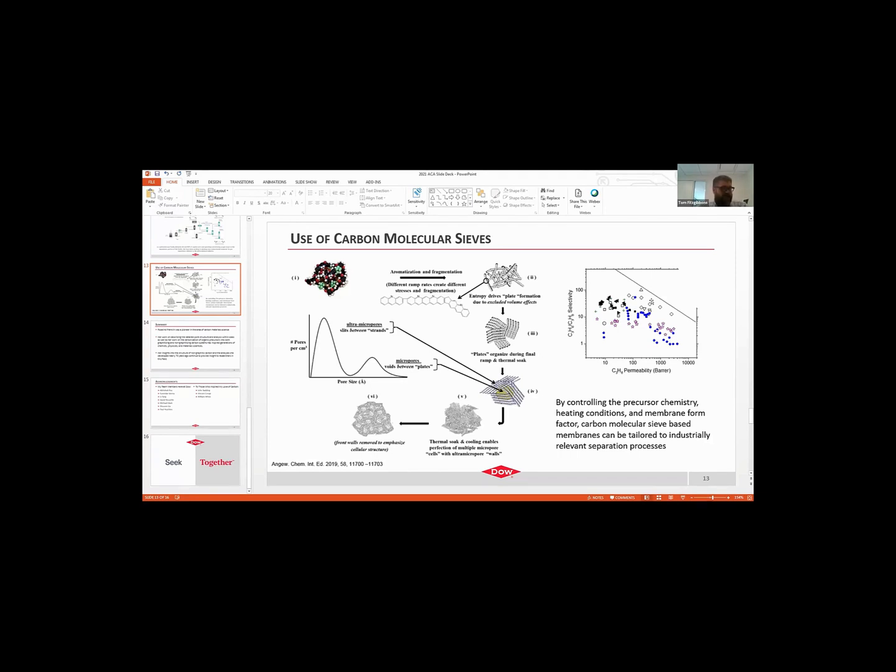One thing that we are investigating that I think is really interesting, and it actually ties into one of the last speakers from before the break, when they talked about Rosalind Franklin's final paper on carbon-based materials in 1957 on the oxidation of carbon. We're seeing that by providing oxidation on some of these carbon materials, it mitigates some of that aging phenomenon, because that oxygen will then passivate some of those layers, or it may remove or chew up, like was shown in the cartoon, some of the more energetic layers that exist in these glassy materials.